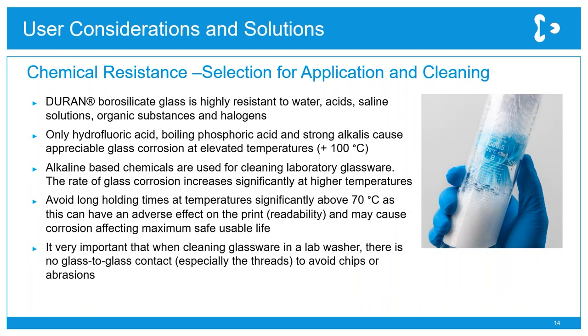In terms of selection of materials, borosilicate glass is a very good choice because it's highly resistant to most chemicals that you're likely to use, and virtually all organic substances. Only very hazardous substances at high temperatures, for example hydrochloric acid, will degrade the glass. Some care needs to be taken with alkaline-based cleaning agents, which can cause corrosion at high temperatures, but it's best to avoid cleaning above 70 degrees and also to keep the cycle as short as possible.